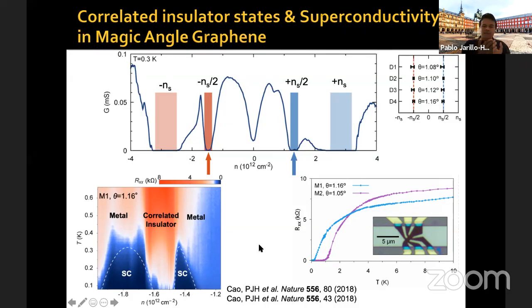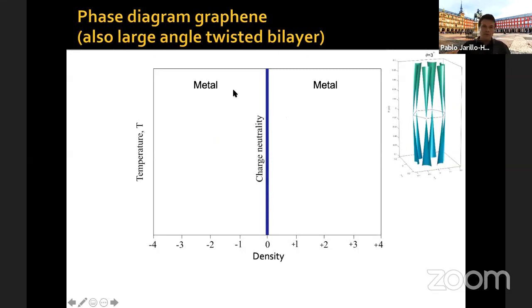So magic angle graphene is superconducting, and this is something which was quite unexpected and has generated a lot of enthusiasm in the community. Now, let me go back a little bit and tell you a bit more about this phase diagram. So this is the phase diagram of graphene and also large angle twisted bilayer graphene, in a plot of temperature versus density, okay? Density here is in arbitrary units. There is only one interesting point, charge neutrality or the Dirac point. When you put your Fermi level or your charge density at 0, there's this interesting Dirac point.